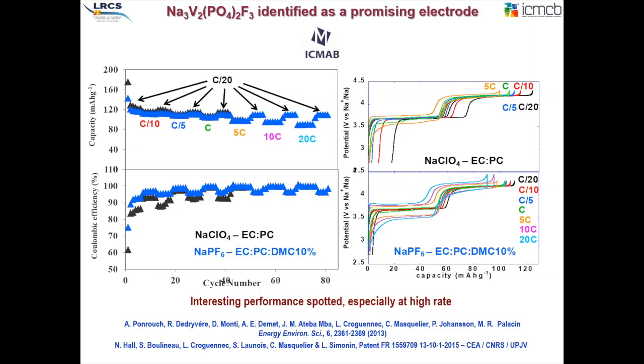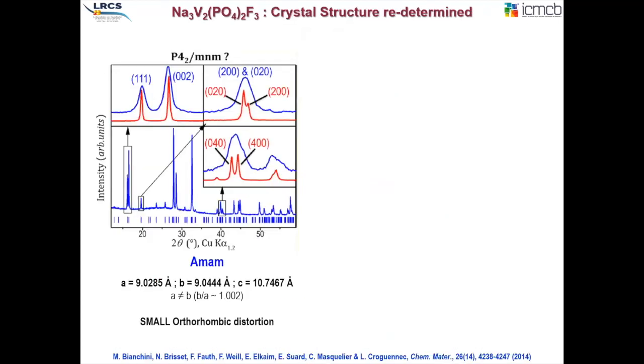So our story with NVPF started close to 10 years ago. Actually, we synthesized this material. It's rather easy to synthesize, I would say, and made many tests with Rosa Palacin from ICMAB in Barcelona. And we immediately realized the main feature being that it really can sustain very, very high rates at the very early stages of our work on this compound. So this was 10 years ago. And so this led us to really start to work on it deeper and in much more detail, as I will demonstrate. But myself, I'm more of a crystal chemist, and I like to look at small little details in the materials we prepare. And NVPF is really fascinating in this sense.